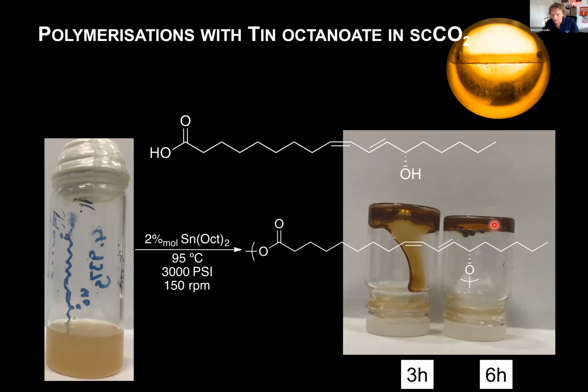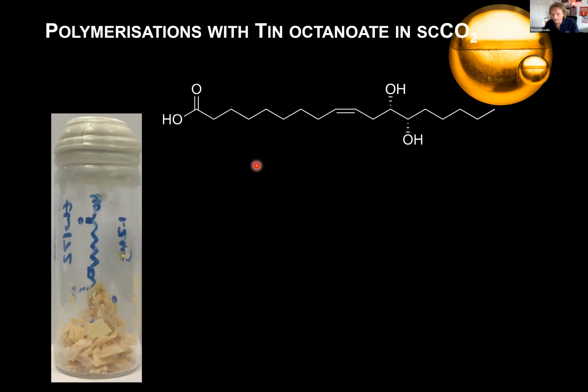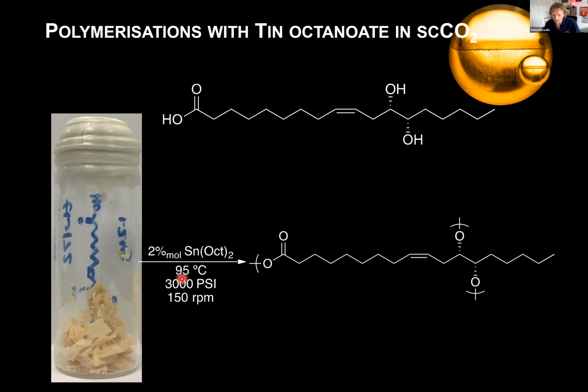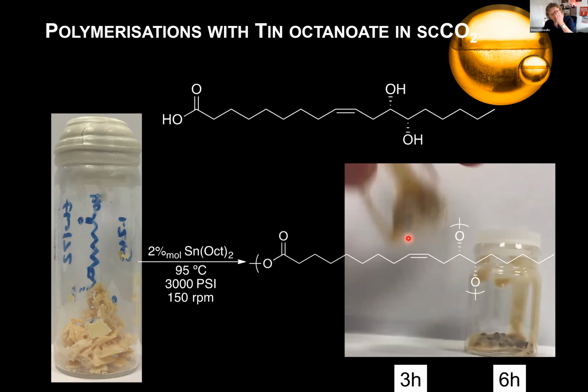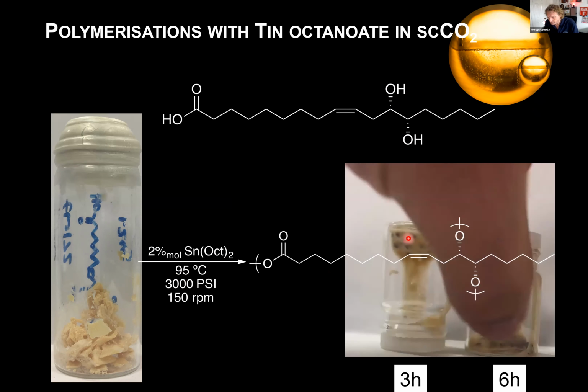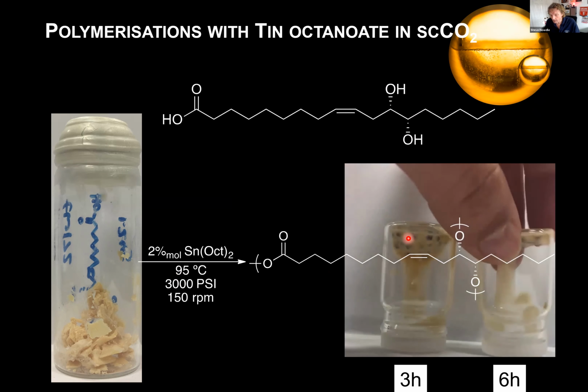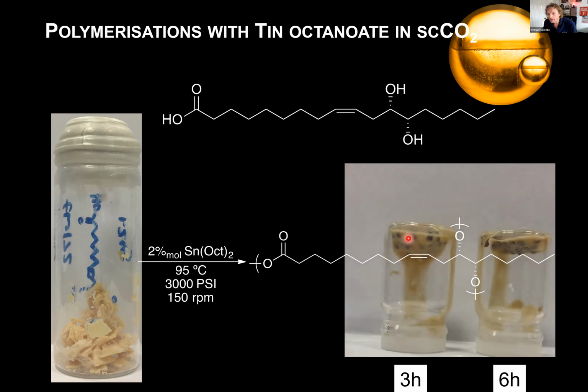With the second monomer, this time we have two alcohol groups on it. So if you're a polymer chemist, you'll realize that this could be useful for branching or cross-linking, and that's exactly what happens. The monomer in this case is a solid, and what we did was we polymerized it in just the same way. What we saw was the formation of some material that was just quite heavily cross-linked network. This enabled us to produce some really quite new materials.